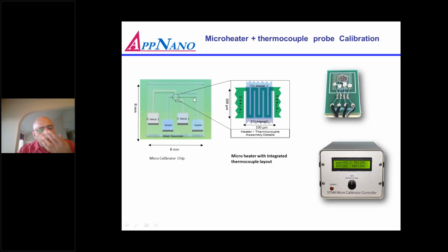So the close-up of this is shown here, where there is a heater and the thermocouple material is basically laid down on top of the heater. So now this thermocouple is getting heated with this heater. So we take a calibrated thermocouple and we calibrate this thermocouple with that heater, and now this is ready for testing and calibrating the thermocouple probe. So this is basically a three-step calibration. You have this calibrated thermocouple and integrated heater assembly, and then you use these two in conjunction to calibrate your thermocouple probe.